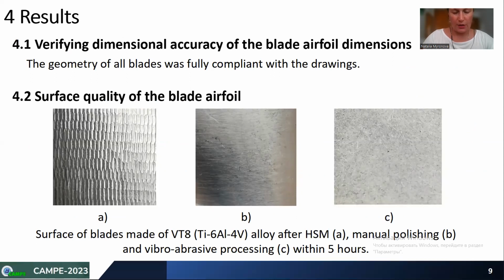Visual examination of the processed surface indicated that after manual polishing, micro defects in the form of grooves were observed. Such defects can lead to the formation of fatigue microcracks. No micro defects were found on the surface after vibro-abrasive processing. Residual traces of milling seams were observed on the blade airfoil profile surface after 1.5 hours of vibro-abrasive processing. When the processing time was increased to 3 hours, the number of traces decreased. And after 5 hours of vibro-abrasive polishing, there were no seams and the surface had a constant characteristic micro relief.